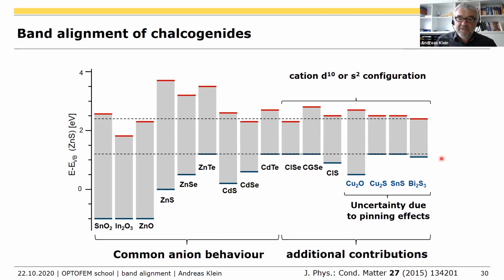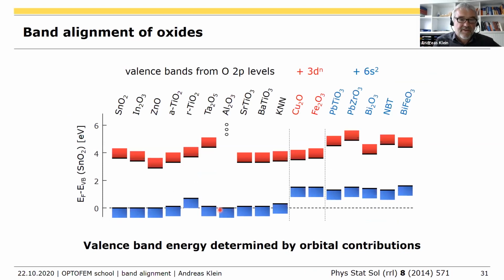Then there are some other materials which also have cation contributions. But for the materials where you can really have only the anions in the valence band, they follow this common anion rule nicely. You can get the same thing for the oxides. You see here the valence band maxima of many oxides which in principle contain only oxygen states: tantalum oxide, aluminum oxide, strontium titanate. One exception is the rutile titanium dioxide, which is a little bit higher in energy. To explain the details, I will do that on the next slide.